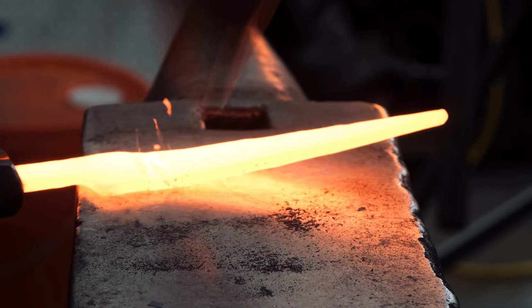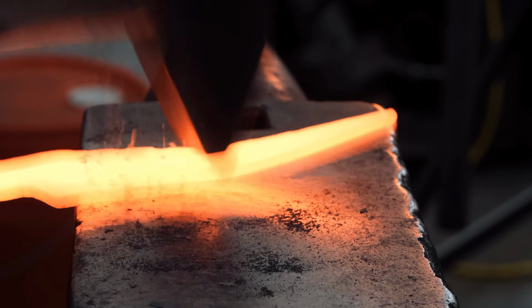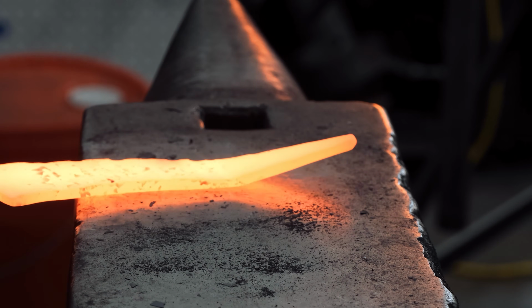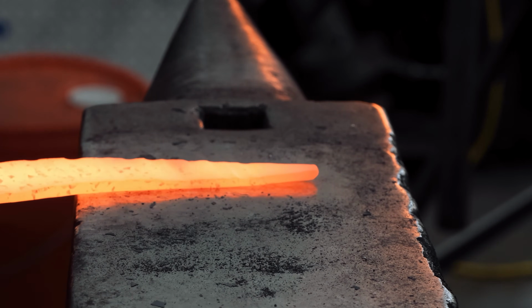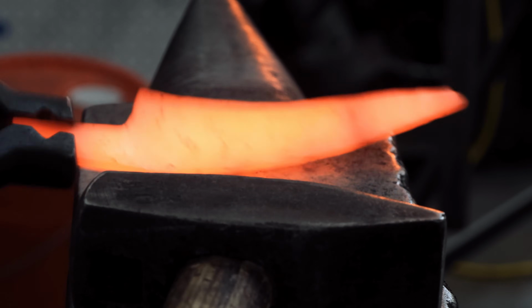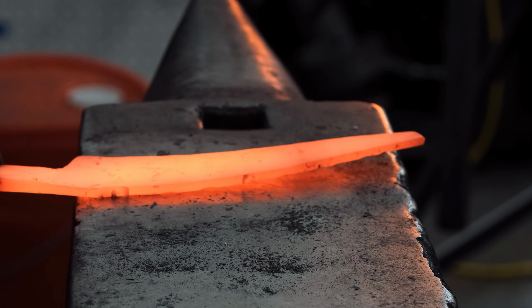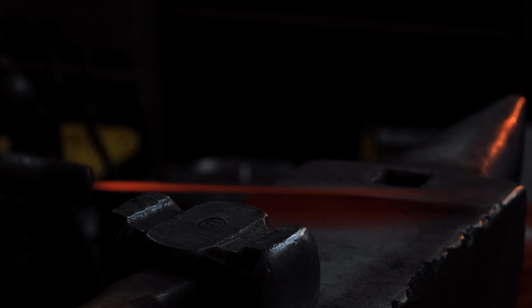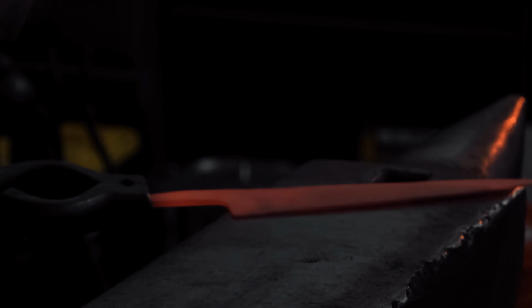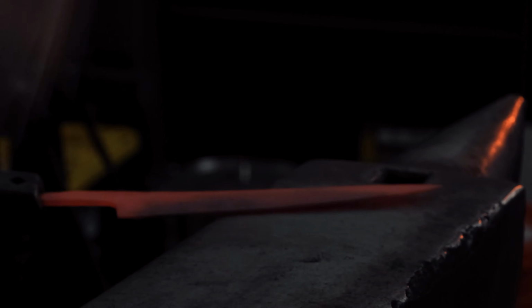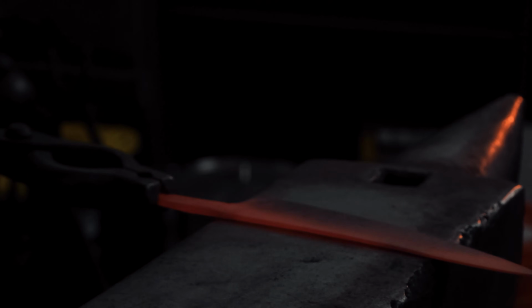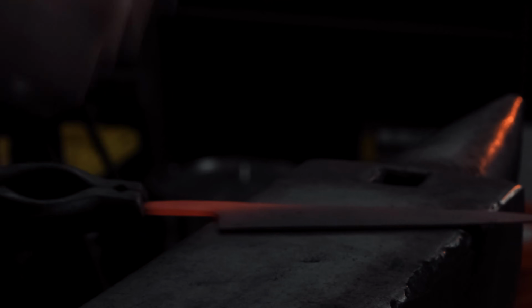And if there's a forge welding step, that's done at fairly high heat. And then after I've welded a billet together, and then I've drawn it out and forged the knife shape, I lower the temperature significantly. In doing so, I get a jump start on grain refinement, and I keep my grains small, and I'm also minimizing grain growth with mechanical shrinkage by hammering, by forging.